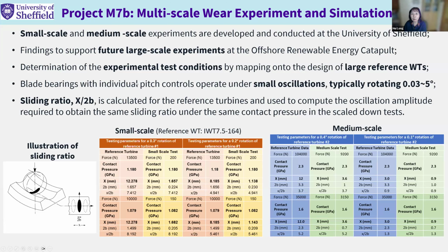The first thing we need to do is to develop experiment test conditions by mapping onto the design of the large reference wind turbine. Two important parameters we need to decide are contact pressure and the sliding ratio. There are some illustrations here. We try to map to the large one, so we make sure what we test at small scale and medium scale can map to similar operating conditions of the large wind turbine.